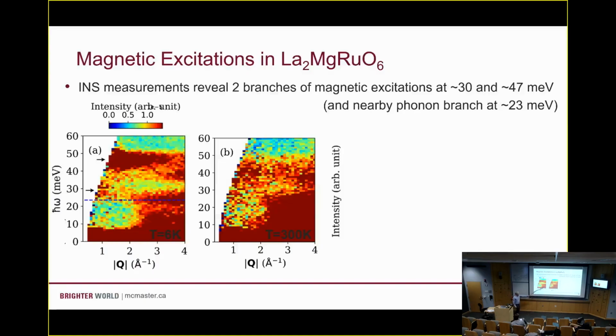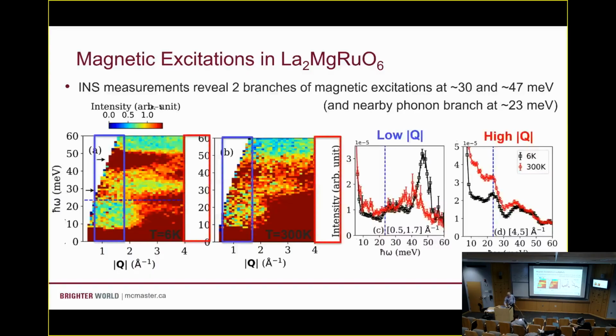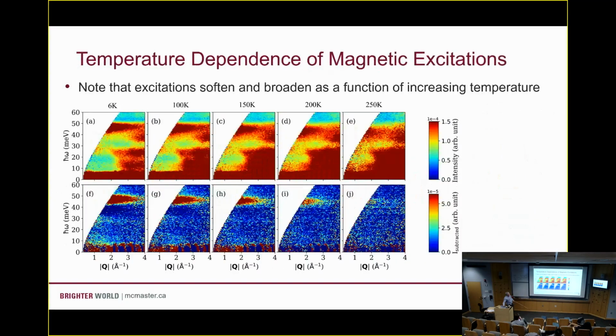You can see this is at low temperature, this is at high temperature here. You can see that this intensity has sort of disappeared. This is perhaps softened a little bit. And you can look at this in line scans by just integrating up the intensity at low Q or high Q. And so the temperature and Q dependence here lets us associate these features with magnetism. Okay? So this is showing us the magnetic excitations, which we think are associated with this spin orbit exciton.